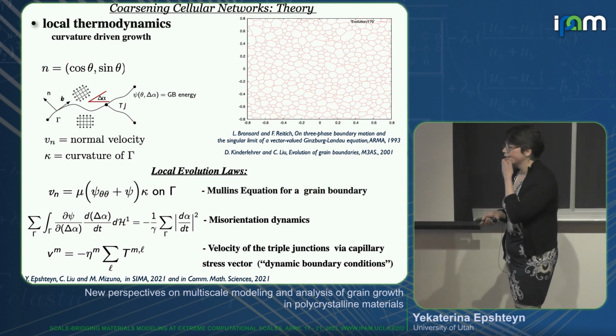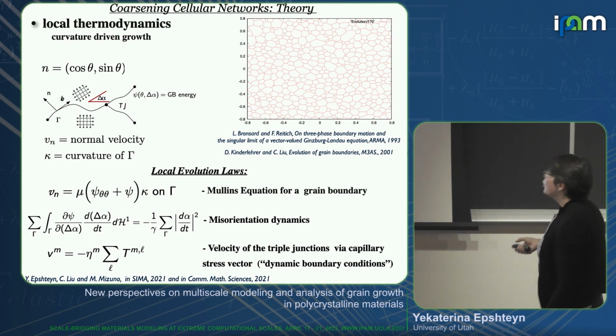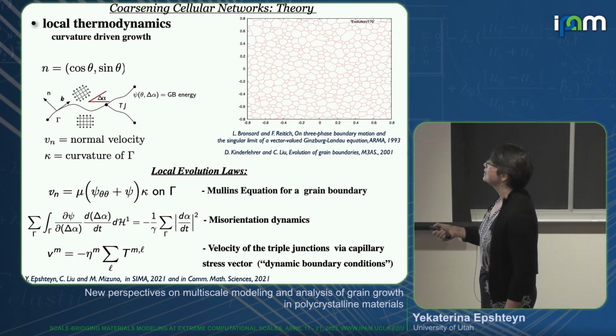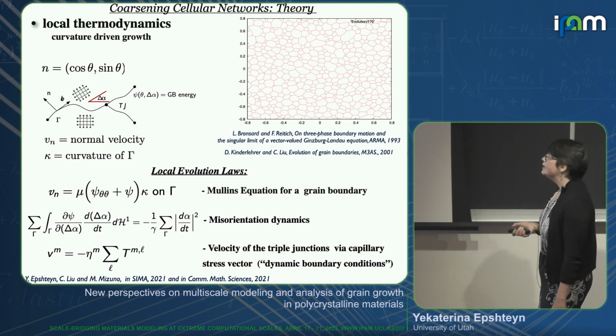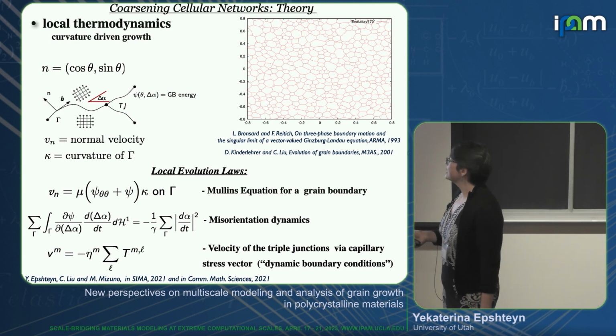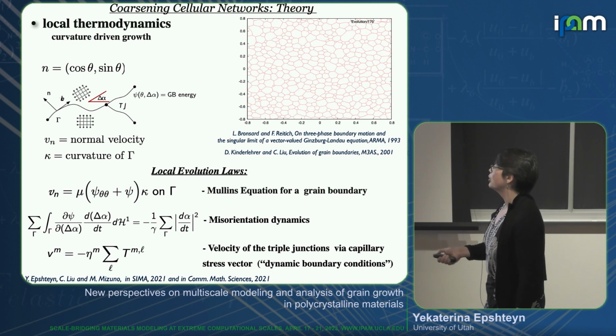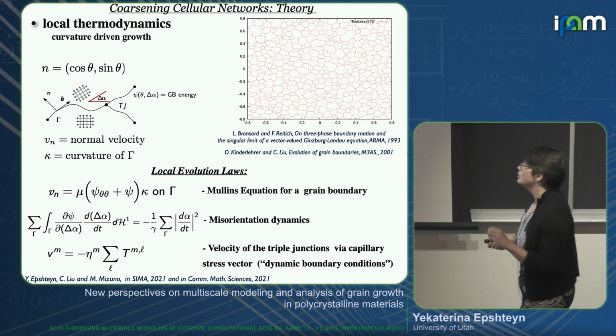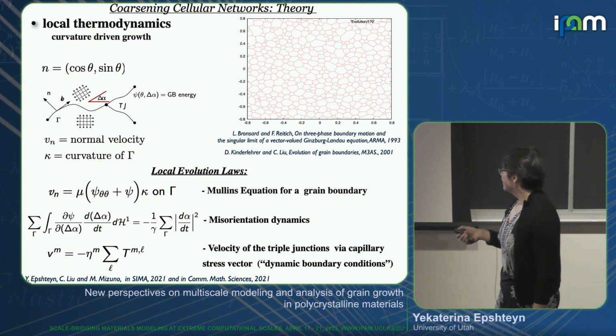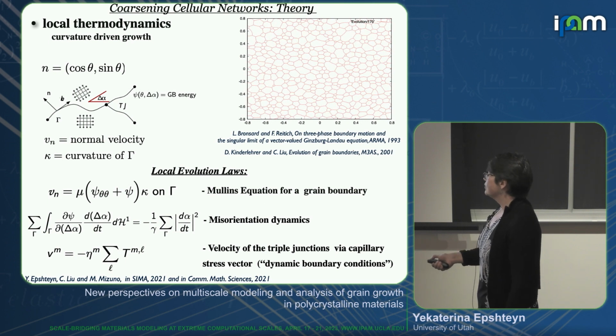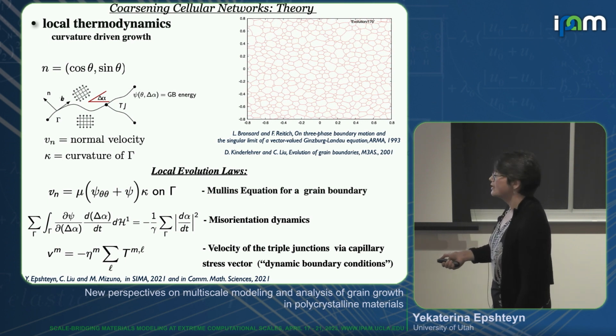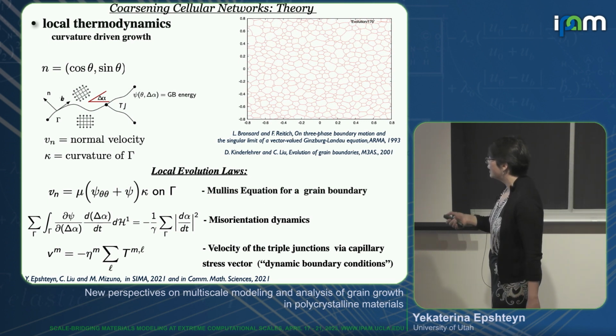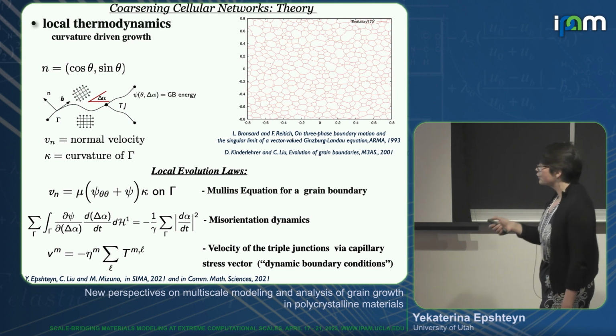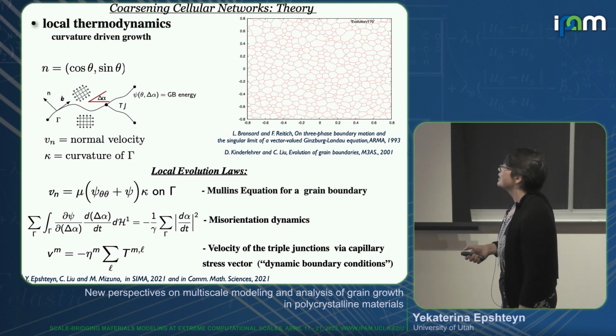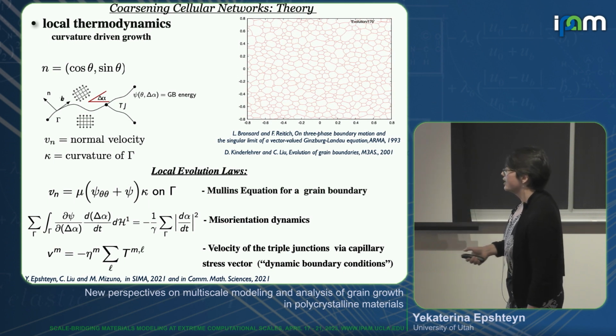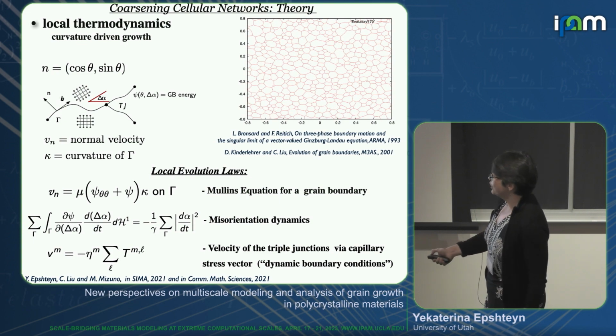So in addition to that, to have a mathematically well-posed system, we also need to impose some boundary conditions at the triple junctions. So in our recent work, we decided to consider more general dynamic boundary conditions and also consider effect of the dynamics of triple junctions itself. And we assume a finite mobility of triple junction. So basically, the normal velocity of triple junction is proportional to the net force acting on a triple junction through the mobility coefficient or relaxation time scale, which is associated with dynamics of triple junctions themselves.